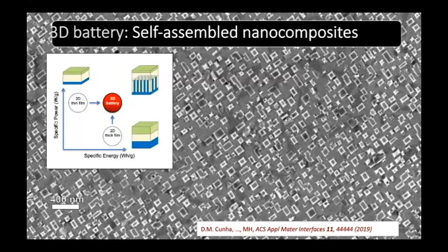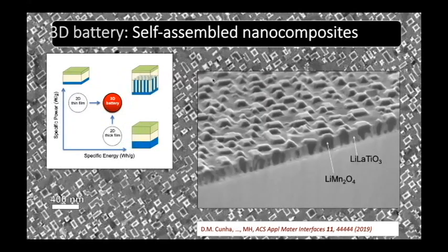In the back of this slide, you can see an electron micrograph of a surface, where you can clearly see these columns within a matrix. And they were quite successful in growing such mixed materials, so-called nanocomposites. Here you can also see in the cross-section the electrodes and the electrolyte material grown in a single run, and you can get this columnar growth there. So now the next step is to incorporate this in a real battery and see whether you can indeed get high specific power versus specific energies.